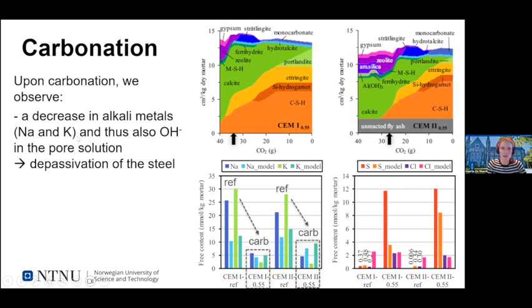And a decrease in available sodium and potassium means that we have a decrease in OH minus and therefore a decrease in pH and a depassivation of our steel. But that we knew. But what was nice too, we could actually see where the alkali went. They go to these silica gels, which actually absorb the alkali.